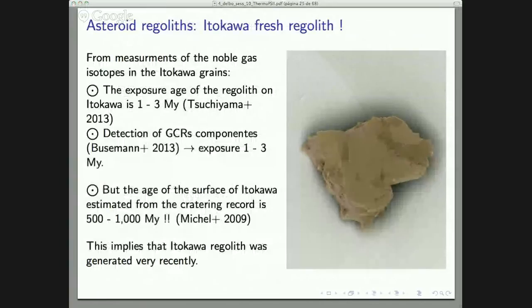And I conclude with two implications of this thermal cracking. So it could be, but it's not sure, that we can explain fragmentation of material on the surface of asteroids much quicker than micrometeorite bombardment. And it's interesting that the exposure age of the regolith of Itokawa is very young compared to what would be implied by the micrometeorite model of Horz. There might be other explanations.